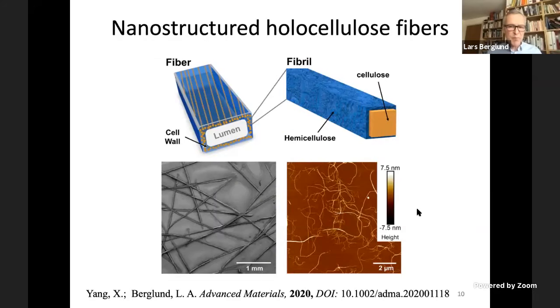And what we have proposed in many of our recent studies is that the fibers themselves, if you do very mild delignification, you maintain cellulose molar mass, you maintain the distribution of hemicelluloses. And if you look at this SEM image, you see that the fibers are really straight. So when we make materials from these fibers, they show extraordinary properties. And we're quite convinced that this is related to the fact that we're preserving the structure of the cell wall so that the cellulose becomes much more efficient in its function.